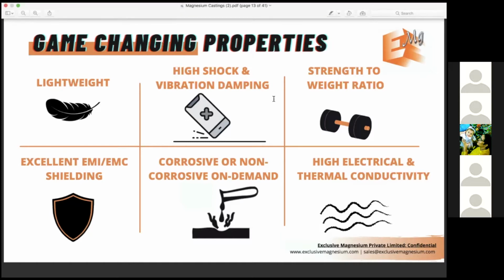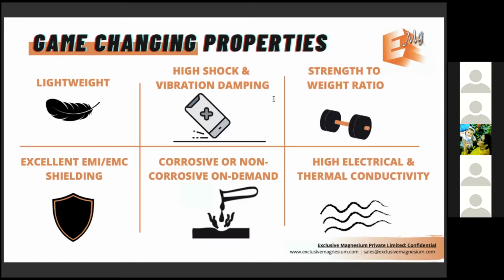Okay. Sure. The third is strength to weight ratio. Even with very thin walls, you'll get very high stiffness with magnesium. Aluminum usually is recommended to have 1.5 or 2 mm wall thickness, whereas magnesium can be cast as low as 0.65. We've done 0.65 wall thicknesses, and even at that, you get significantly good strength or stiffness, which is required for the use case.